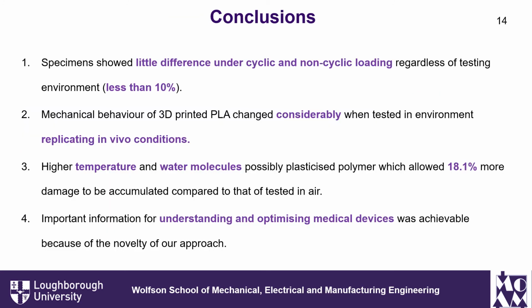To summarize our findings, we showed that tensile testing under cyclic and non-cyclic loading resulted in very little difference in terms of ultimate tensile strain and strain at fracture. So this information can be useful for people who design new medical implants. Furthermore, we showed that the correct assessment of polymer for biomedical application is important. Specifically, tensile testing submerged at 37 degrees under cyclic condition resulted in more damage to be accumulated quicker compared to tested in air. So people should consider this for future study. And all of this information was only possible through our novel approach of using our own tensile testing specimens other than using the current ASTM standards.